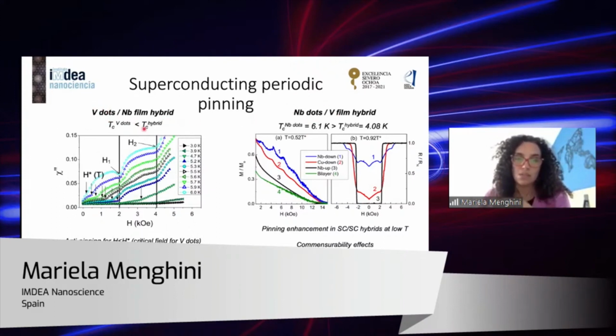The idea is to change the roles. In the first case, the transition temperature of the periodic array is lower than that of the hybrid system, and there they have seen some anti-pinning effects at magnetic fields where the vanadium dots are superconducting. In this other case, where the critical temperature of the superconducting array is larger than the hybrid, they have seen some enhancement of the pinning in these superconducting hybrid structures at low temperatures, and they have also reported commensurability effects, right? So these peaks in the magnetization when you have matching fields.